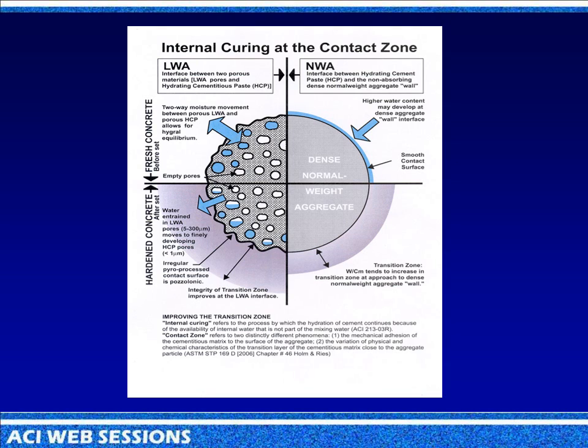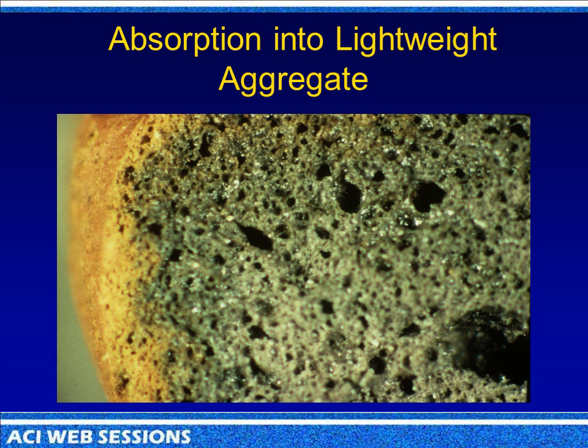Somehow, because of the porosity of the aggregate and everything, you get more of an equilibrium effect. And then as soon as it starts hardening, this moisture comes out of the aggregate and comes in here, and you get a lot better, what we call a contact zone. And here's a better demonstration. Or here's just an absorption thing.